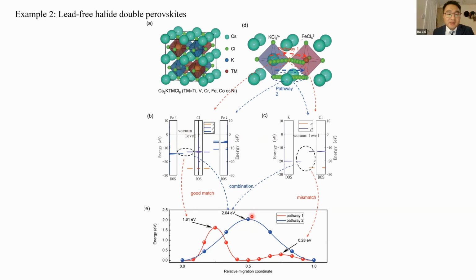We also found that the EB of pathway two is 2.04 eV, which is almost equal to 1.61 eV plus 0.28 eV. This is because the former part and the latter part of pathway one correspond to the breaking of Fe-Cl bonds and K-Cl bonds, whereas pathway two indicates that both bonds were broken.